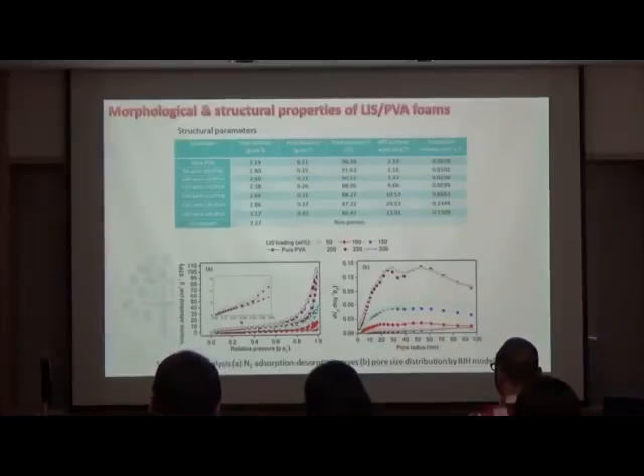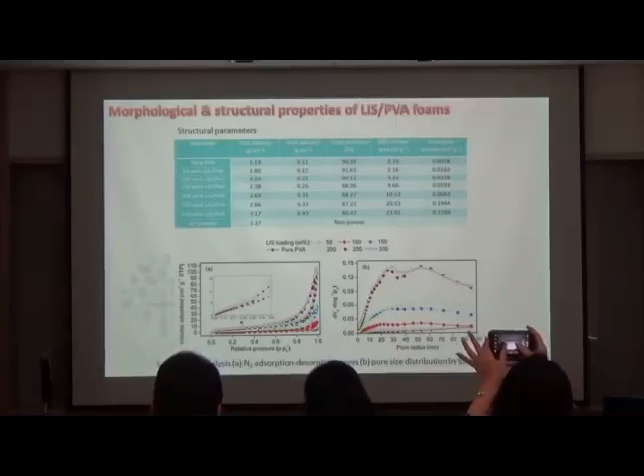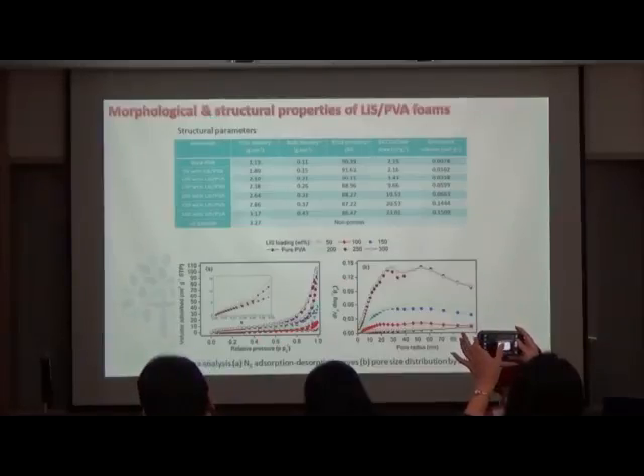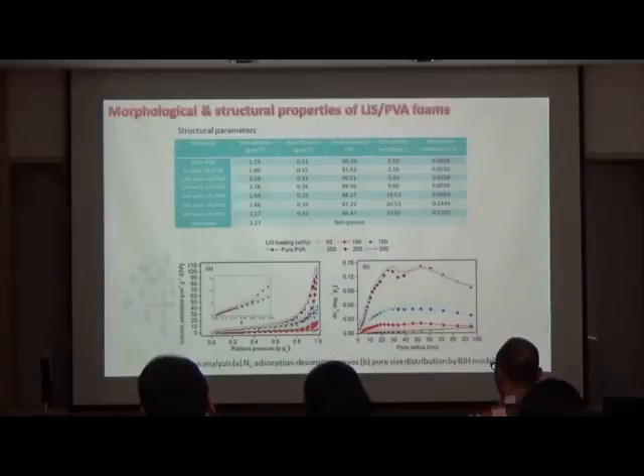In the nitrogen adsorption-desorption branch of the pure PVA and the composite foams, all samples exhibited a type 4 isotherm, and the hysteresis between the adsorption and desorption indicates that apart from the macroporosity of our foam, there is also mesoporosity. Therefore, the hierarchical pore network of our foam samples is composed of macropores and mesopores. Furthermore, the BET surface area increases with the LIS loading. This indicates that, one, there is an increase in the creation of bimodal distributed mesopores, and two, the increase of the mesopore volume correspondingly increases the BET surface area.